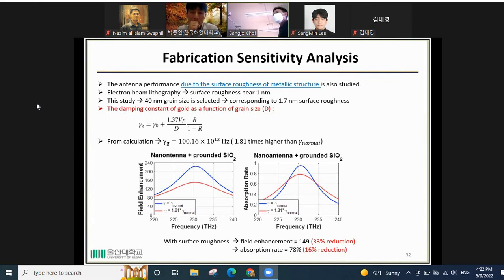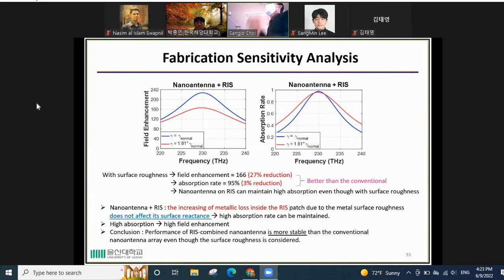So this is the field enhancement and also absorption rate of the nano antenna. So we can see from here with the surface roughness, field enhancement reduced to 149, which is 33% reduction, and also absorption rate experienced 16% reduction with the surface roughness. And this is the nano antenna combined with RIS. With the surface roughness, field enhancement is 166, which is 27% reduction.